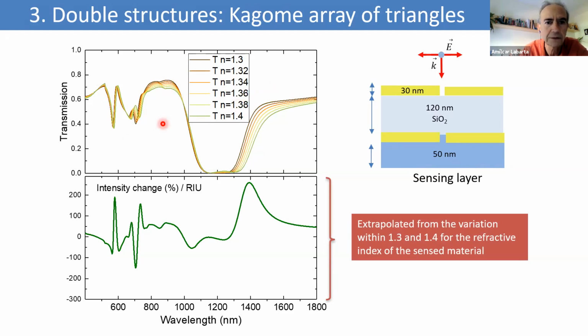From these curves, we can compute the intensity change percentage per refractive index unit. And you can see that there are some wavelengths at which the percentage of variation is around 200%. This is enough to build a sensor with a very good performance. Okay.